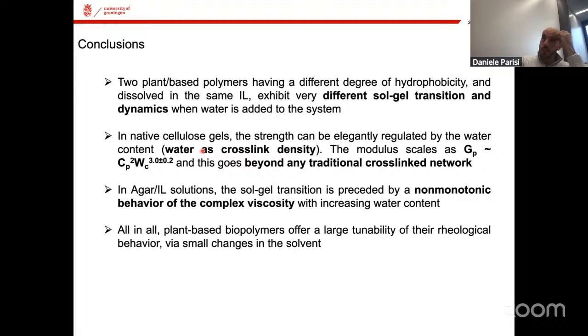And we came up with some scaling laws that are really beyond any traditional cross-linked network and allow us to design gels for 3D printers, for instance bioinks, or gels in general for applications. So, agar and ionic liquid solutions: we have this unprecedented reported non-monotonic behavior of the viscosity with increasing water. So there is a minimum there. And in general, the message is that plant-based biopolymers offer a large tunability in rheological properties just by playing with the solvent. And we are just scratching the surface, I would say, because there is really a lot to know about these polymers.